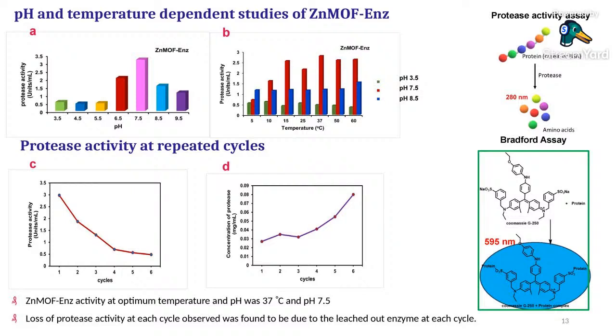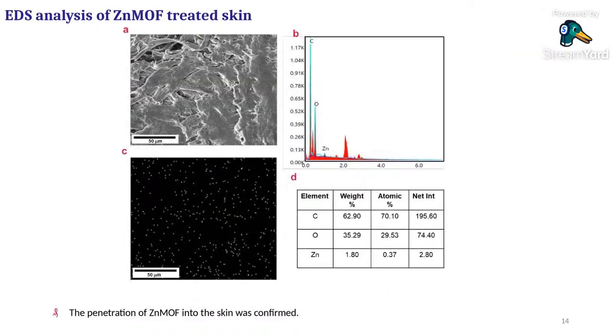Up to 4 cycles, there was not that much leaching happening. After the 4th cycle, yes, a lot of protease is leaching out. So we stuck with the process for up to 4 cycles only. Then we moved on to the application itself. We took a small portion of the skin and coated it with the immobilized protease on zinc MOF. We actually coated the surface of the skin that has the hairs.